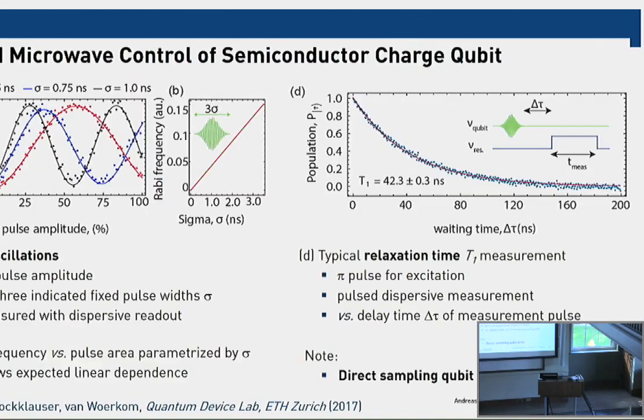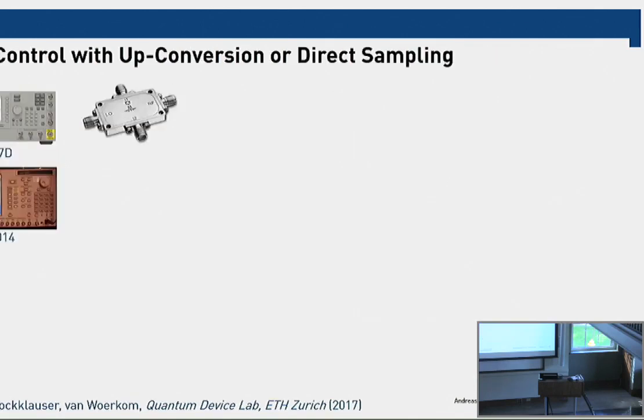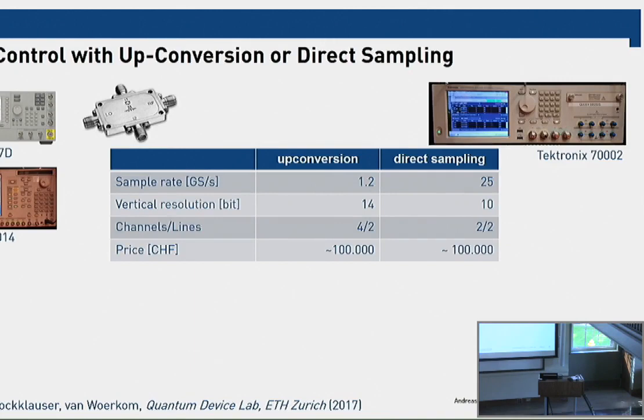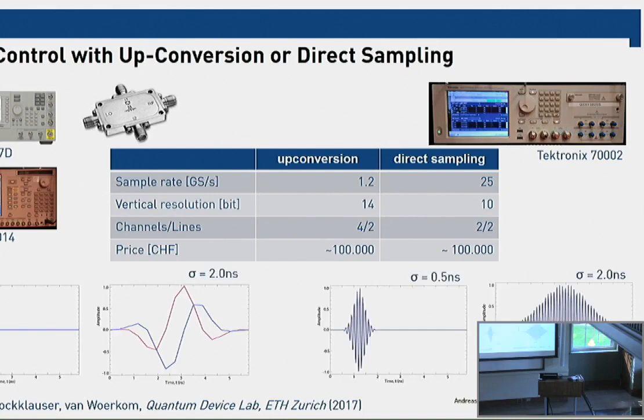Maybe one thing that was nice in this experiment that we did is that it was actually the first time that, rather than doing the standard thing that one would usually do, using a CW microwave source, a mixer, and an arbitrary waveform generator to create these microwave pulses, we decided to go for a direct synthesis signal generator, which is not cheap, but which can do 25 gigasamples. And what is nice about that is that you can now define not only the envelope of the microwave pulse, but you can define the amplitude at every point in time.